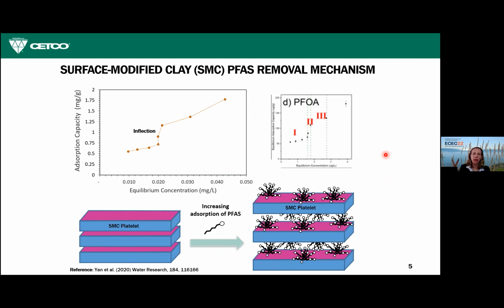And this leads to a unique absorption mechanism, which is shown here. This is another cartoon showing the same thing, the d-spacing increase of the clay, as the PFAS sorbs in the interlayer spaces. So basically, this is a plot of absorption capacity versus equilibrium concentration.